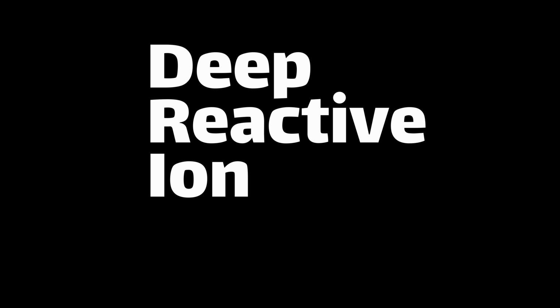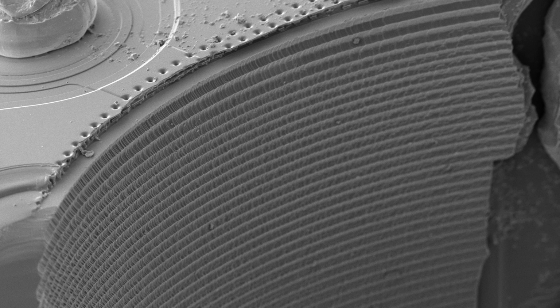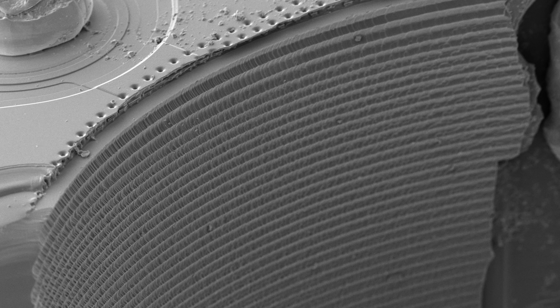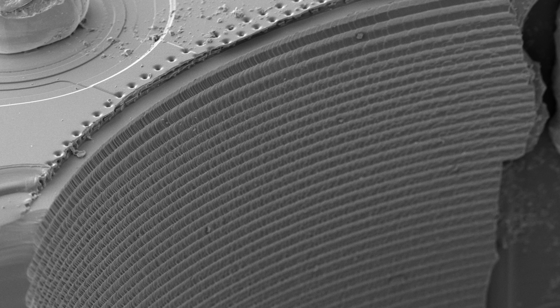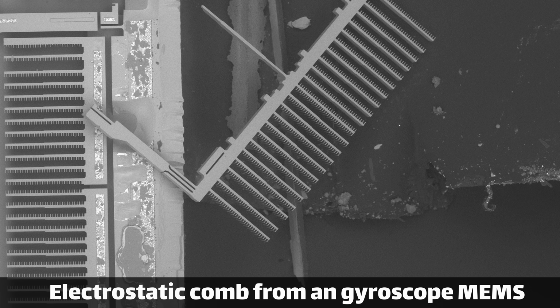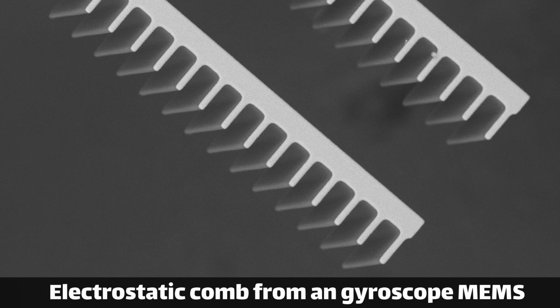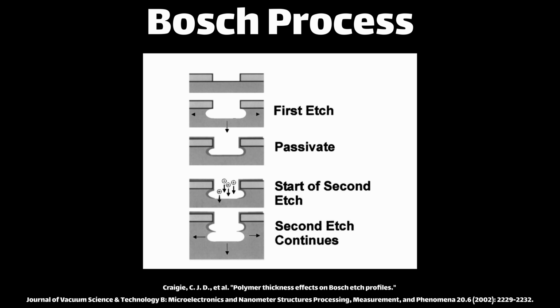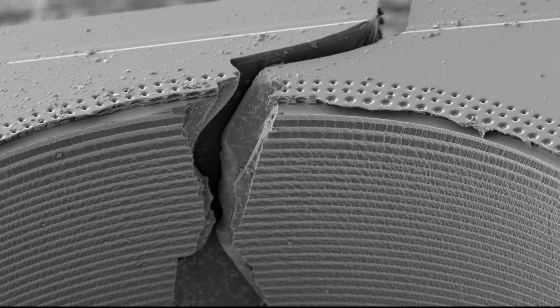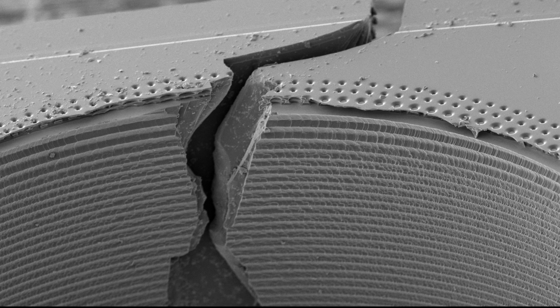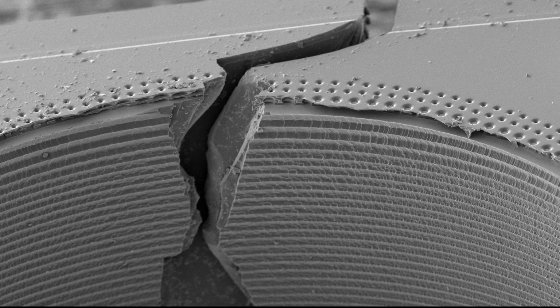This is characteristic of a process called deep reactive ion etching, or DRIE. DRIE probably deserves a whole video on its own because it's a really cool technique. But in short, it's a way to etch very deep and straight profiles in silicon. DRIE is performed in a number of steps, and each step leaves behind one of these ridges. So we can see that this wafer was subjected to dozens of etching steps to get through the full thickness.